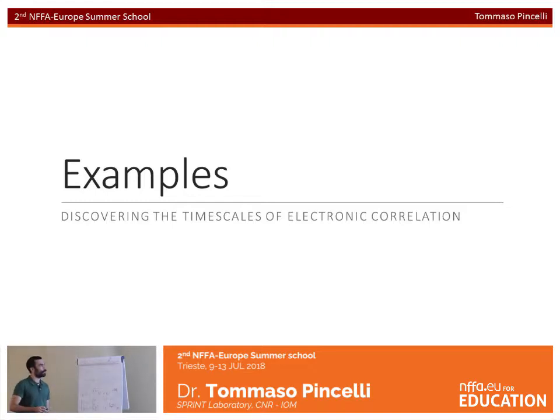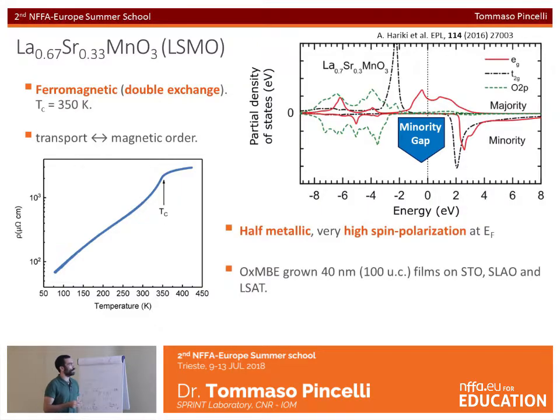So we studied one sample that is a magnetic oxide. It is ferromagnetic, and the movement of charges in the material is obtained by a double exchange mechanism in which electrons hop through the ions in the crystal only if the magnetic moments of the manganese ions are aligned. And this couples strongly the transport and the magnetic order and creates an electronic structure close to the Fermi energy that is exotic. It's half metallic, meaning that the material is a metal for one spin state, but a semiconductor or an insulator for the other spin state. So we have a virtually very high spin polarization at the Fermi energy, and peculiar magnetic properties.